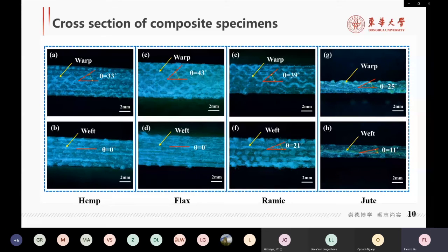It's obvious that the warp crimps of the four fabric composites were significantly larger than those of the weft. Among them, hemp and flax weft yarns had little crimp, ensuring a high rate of fiber strength utilization, and the crimp angles of ramie and jute weft yarns were about half of those in the warp yarns. This could effectively increase the tensile strength and moduli of the composites in the weft direction.